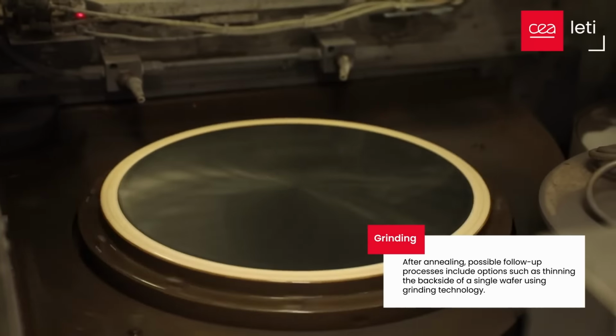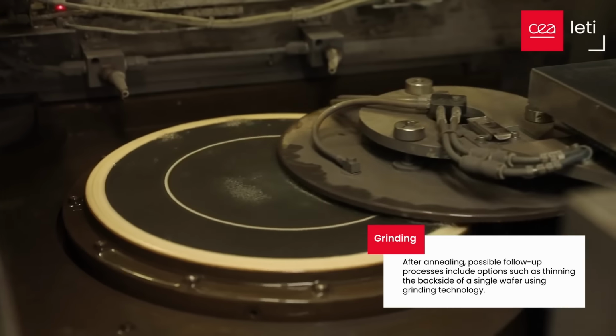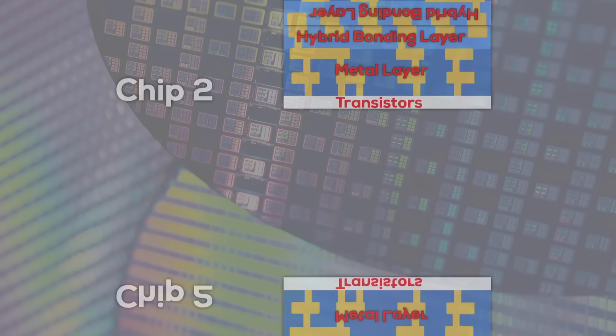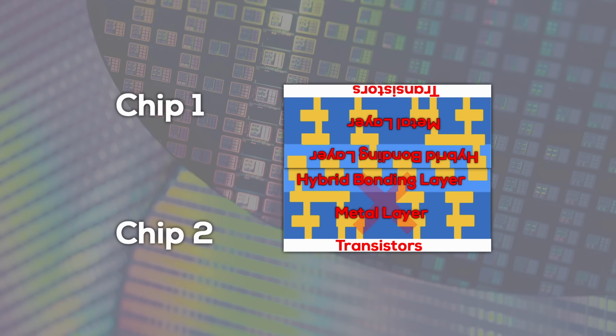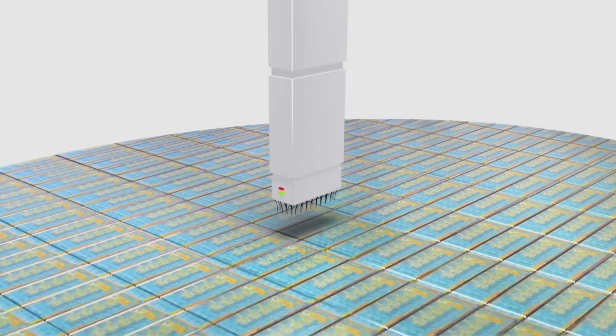But there's one disadvantage to this approach. When you bond wafers to each other, you can't bin the chips beforehand. You have to work with what you got. That means that some of the top and bottom chips will have defects. You could end up with a working cache chiplet on a defect CPU or vice versa. That's where chip-to-wafer comes in. In this hybrid bonding process flow, the wafers are cut and binned before the bonding process, and only so-called known good dies are selected for the hybrid bonding.